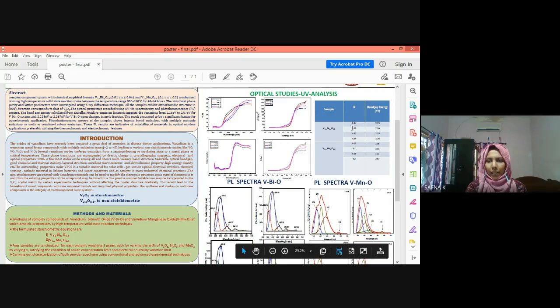And this is the estimated bandgap energy using the Kubelka-Munk function. From this, it is clear that as the mole concentration increases, the bandgap energy of the VBIO system increases, which can be explained using the Burstein-Moss effect. While in the VMNO system, as x increases, the bandgap energy decreases, since as the free carrier concentration increases, the bandgap widening is counteracted by a narrowing caused by the correlated motion of charged carriers.